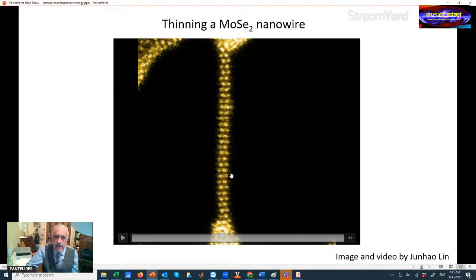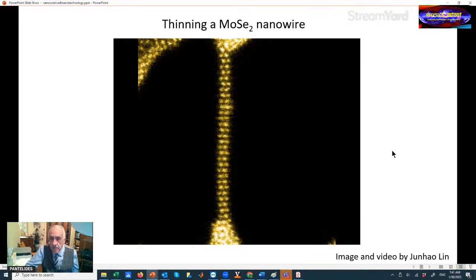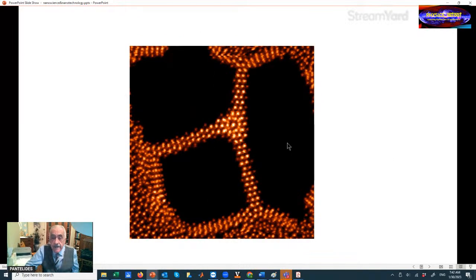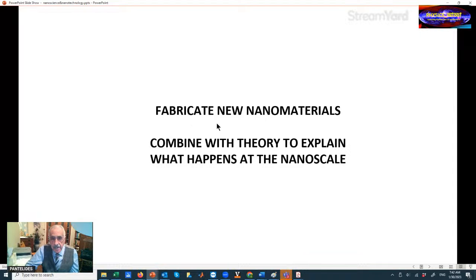And we calculated that these nanowires are metallic, which was very significant, and we demonstrated subsequently with experiments that they are metallic. And this is back to MoS2. By making junctions like that, and these nanowires being metallic, you realize that you can build devices on a monolayer and then make nanowires on the monolayer and connect them so that you can have a circuit on a monolayer. So these are visions of the future where electronics may go someday. A lot of devices have been fabricated on two-dimensional materials, and some small circuits. But we are going to go to electronics. You'll see how many circuits you need to have functioning computers.